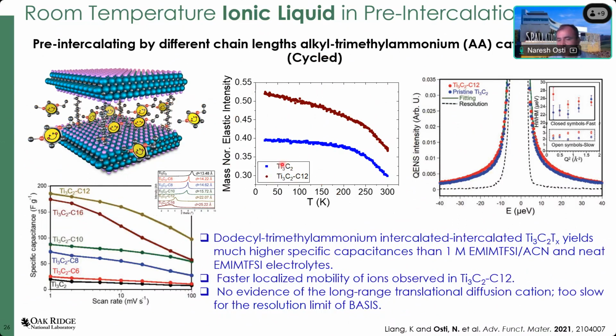Now, we took the C12 system and compared the elastic intensity with that of the pristine MXene. You can see significantly higher intensity coming from the C2 system. It means that it has much more hydrogen-containing species in between the layers. That confirms the ionic liquid is in between the layers.